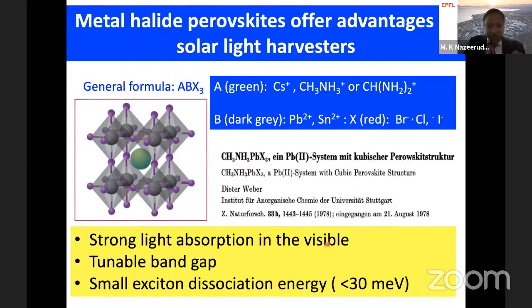Another striking important property of this material is exciton dissociation energy, which is very small. What does it mean? When you shine the light on this material, the carriers are instantaneously getting separated and collected at the charges. They don't form the exciton in the process. And this is one of the main reasons why the efficiencies of these solar cells are so high.